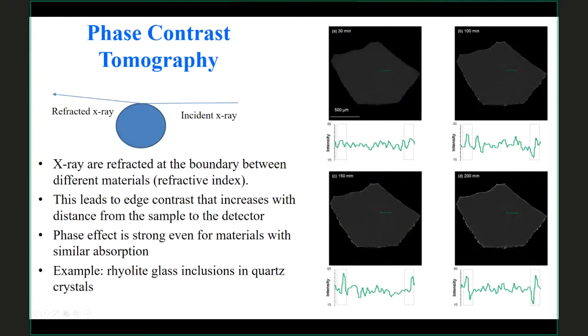So, just say a little bit about a few other kinds of tomography. The first is phase contrast, and we may actually do a phase contrast experiment today. Phase contrast takes advantage of the fact that we've been modeling the interaction of the X-rays with matter as a pure absorption phenomenon, but in fact, X-rays can be refracted as well as absorbed. And as an incident X-ray comes to the boundary between, let's say, a solid here and air here, it's bent slightly. Just as visible light would be,